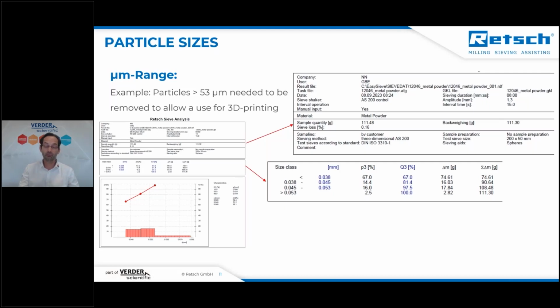So we were able to remove this fraction of bigger particles from the whole sample, so that we were able to recover 97% that then can be used for the 3D printing process without any problems, of course. It's also possible to get lots of other information or characteristics which can be individually set in the software to be calculated and give you more information about the particle size distribution of your product. Okay, so this is just a sieve analysis, or the result that you can see. How is this result produced?